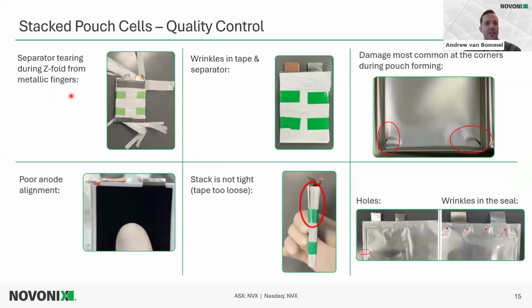So, some quality control issues for stacked pouch cells. Here's an issue of separator tearing during the Z fold from those metallic fingers that grab the separator. Wrinkles in the tape and the separator. In this case, there's poor anode alignment, so we want to be sure that the anode has an overhang. In our case, we do 1 millimeter overhang for both our cylindrical cells and our stack cells.